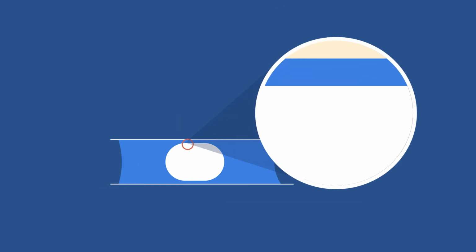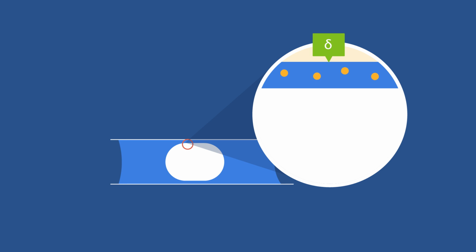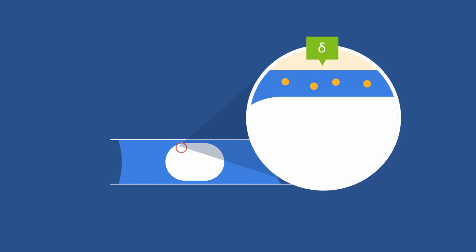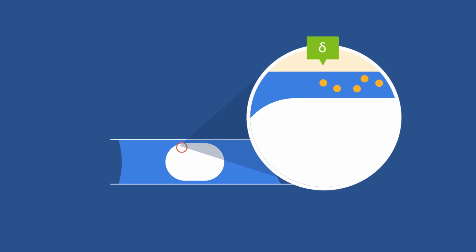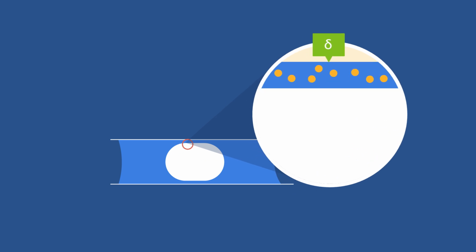However, the solution in the film is more concentrated than that because it is enriched by diffusion from the bulk solution that is more concentrated as it must satisfy the higher solubility of the crystal tip. Therefore, there is a supersaturation in the liquid film so that the crystal sides have a drive to grow. However, they cannot do that because they are prevented from making contact with the pore wall because of surface forces, as explained in our video, Chemo-Poromechanics of salt damage.